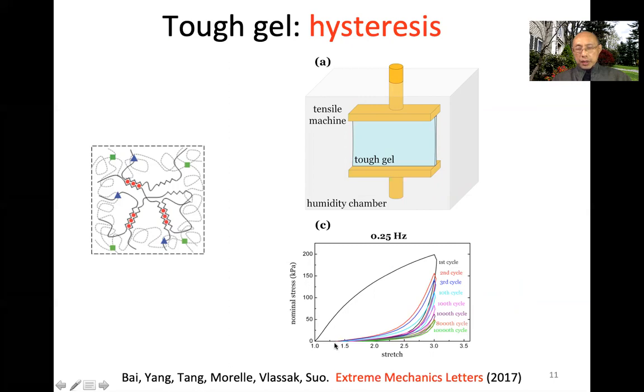So when you do the second cycle of reloading, the ionic crosslinks don't rezip. So the second cycle becomes much lower. And as you go through more and more cycles, this is 1,000 cycles, 10,000 cycles, your hysteresis curve just keeps going down. It means you damage this material, unzipping ionic crosslinks more and more each cycle. So that's essentially what causes fatigue behavior.